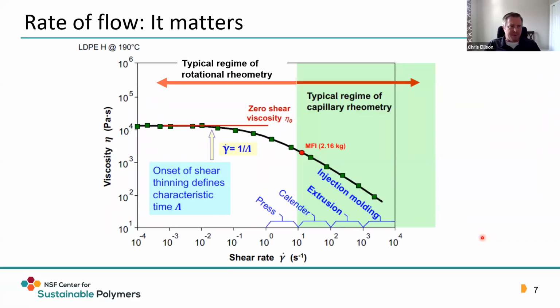Just to show a few examples of this, I'd like to focus on the rate of flow and how it can affect the way in which a material behaves. Here I'm showing low density polyethylene, a plot of viscosity versus shear rate. You can see that the viscosity the material exhibits in the process can be very different depending on the shear rate or characteristic shear rate of that process. Injection molding, extrusion, calendering, pressing, or molding can all take on different characteristic shear rates.